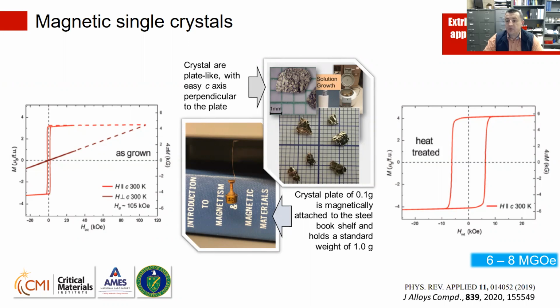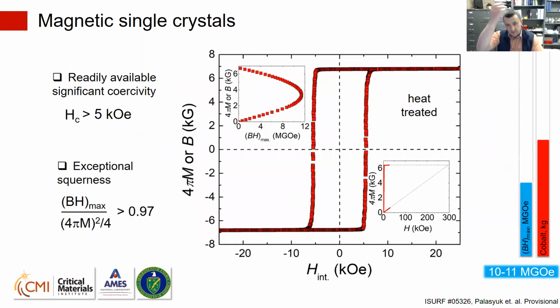Extrinsic characteristics appear readily after the heat treatment. This fact alone attracted our attention very strongly. We developed these single crystals and found, in fact, that we already reached gap performance, because this, for example, is already performing within the gap. It's more than 10 megagauss oersted. What is even more interesting is that it has exceptional magnetocrystalline anisotropy, and the indicator which shows cobalt per megagauss oersted starts to change. It's not that negative anymore.